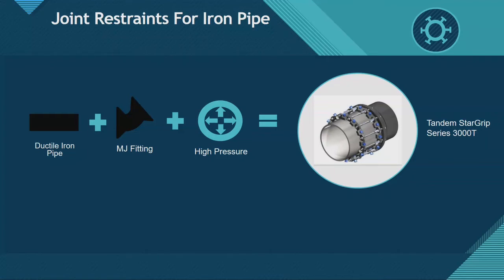When you do it though, you have to be careful, because now your T-bolts, hopefully you can see where I'm pointing here, your T-bolts here are a lot longer. So you need to first put this first restraint on, put your nuts on the T-bolt, thread them all the way down, and tighten those up. And you need to torque those to the proper torque, and it depends on the diameter of the pipe what that torque is. You cannot get a deep socket on there to do the torque settings, so you can use what's called a crowfoot.